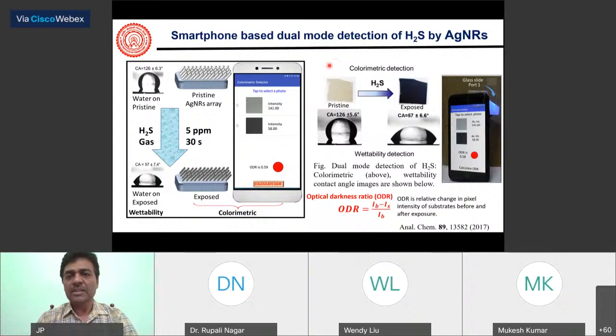Let me go to the bacterial detection using this silver nanowire. The gist is that most of these biopathogens, like bacteria, if you talk about living cells, have a metabolic system such that they evolve hydrogen sulfide gas. By detecting a small amount of hydrogen sulfide gas from these pathogens, one can detect whether they are alive or dead.